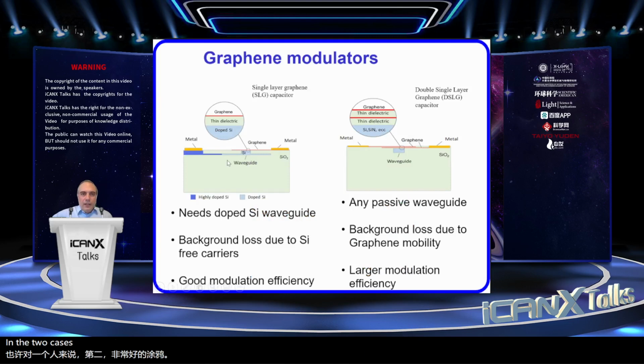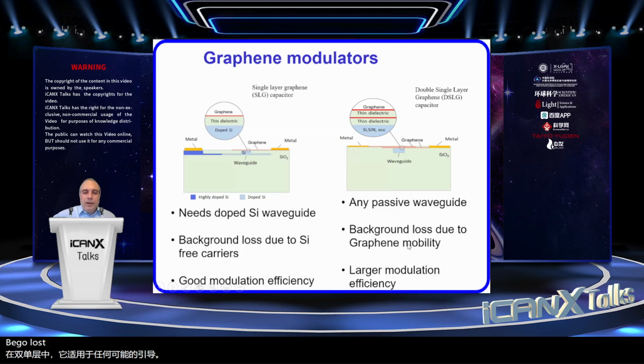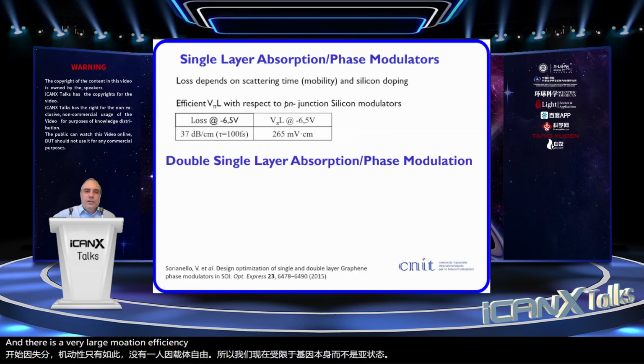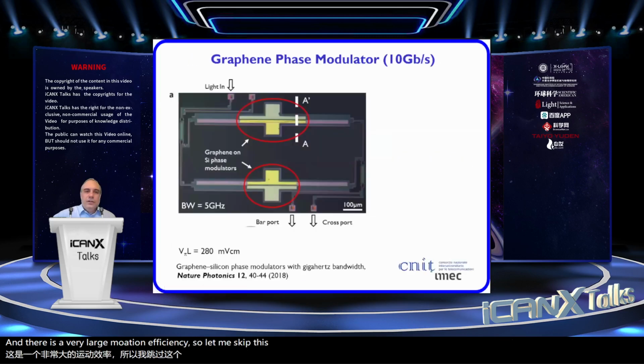So in the two cases, if we use only a single layer, we need a doped silicon waveguide. There are background losses due to silicon free carriers, but it still has good modulation efficiency. In the double single layer, it works for any passive waveguide. There is a background loss due to the graphene mobility only, not the one due to the free carriers. So we are now limited by the graphene itself, not by the substrate, and there is a very large modulation efficiency. So let me skip this slide and let's go to the next one.